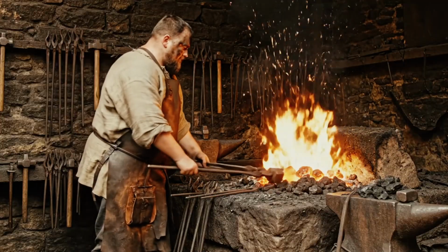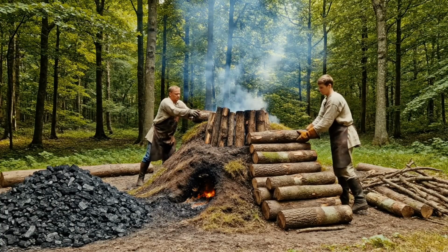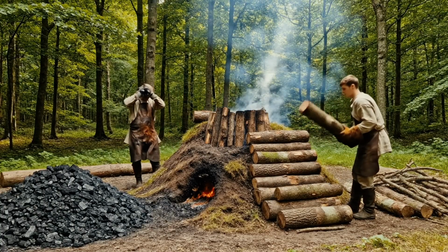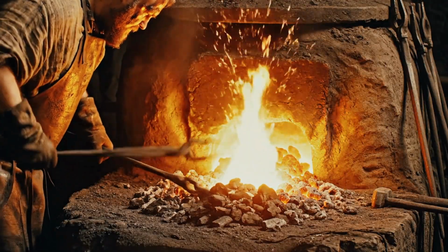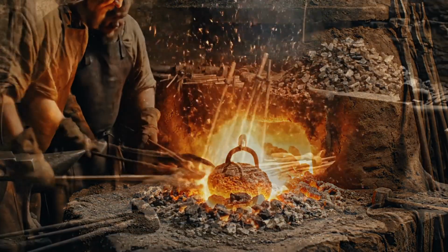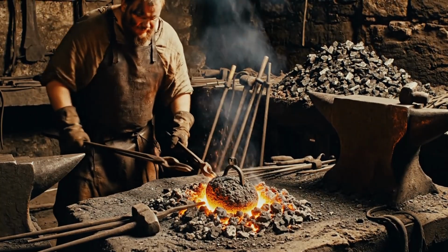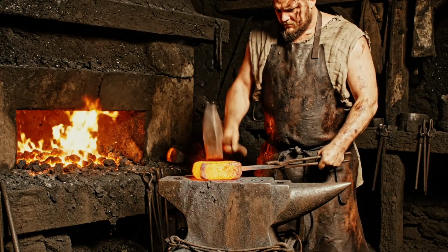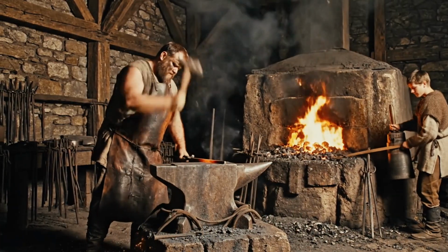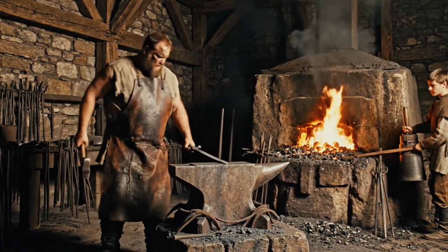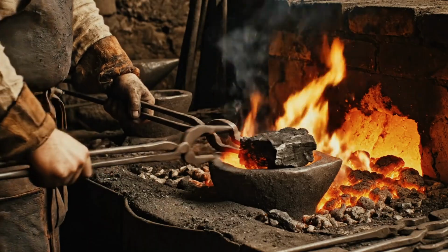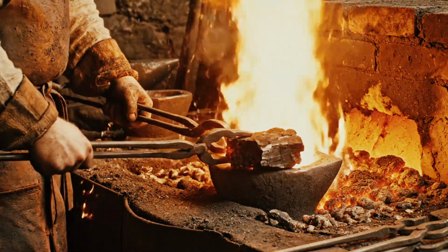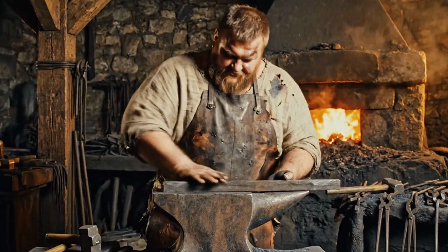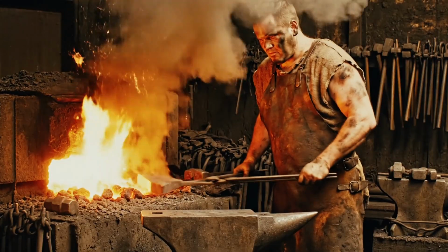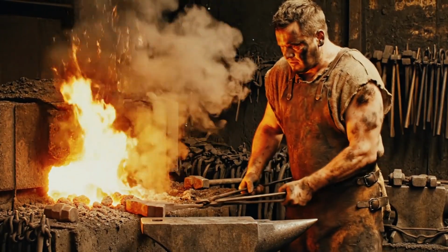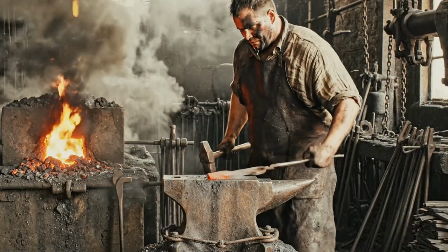The situation changed dramatically with the onset of the Industrial Revolution and the transition to coal and coke. The Earth's interior contains not only energy, but also the periodic table, including sulfur. Sulfur is a real poison for iron, making it brittle and prone to oxidation. When coke burns, sulfur is eagerly absorbed by molten metal, becoming an integral part of it. It is almost impossible to remove it completely. One can only reduce its concentration to an acceptable level. But even small doses of sulfur trigger processes within the metal that lead to its destruction.